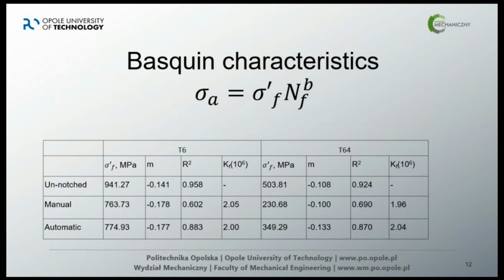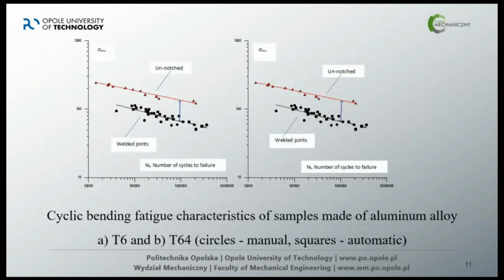If you calculate it for 10⁶ cycles, for unnotched and manual, we see the fatigue notch coefficient is about 2.05 for T6, and for T64 1.96, coefficient 2.04. So generally, for welded specimens, the fatigue characteristic is moved nearly 2 times down. So we see this coefficient is nearly 2.